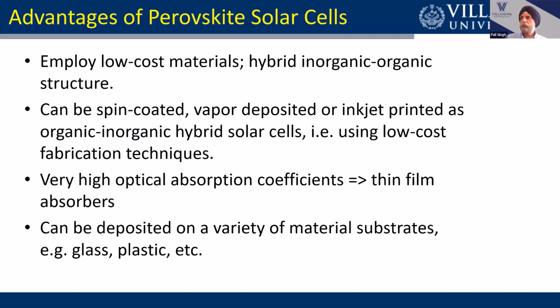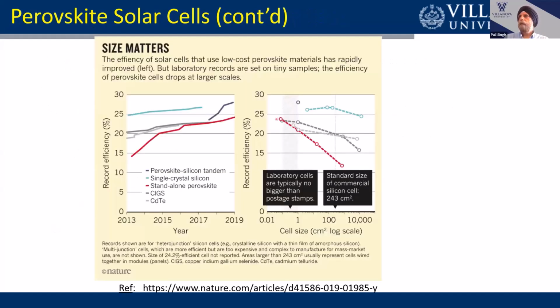And it can be deposited on a variety of material substrates. So you can deposit them on glass. You can deposit them on plastic if you want a flexible solar panel. So there are a lot of advantages of using these perovskite solar cells. The challenge has been to come up with larger size solar panels. So the initial research, you can see the efficiencies were rising very quickly, as I mentioned earlier. The red line here represents a standalone perovskite, and then the black line, or dark purple line, represents a perovskite silicon tandem. And you can see that the highest efficiency is approaching 28%.